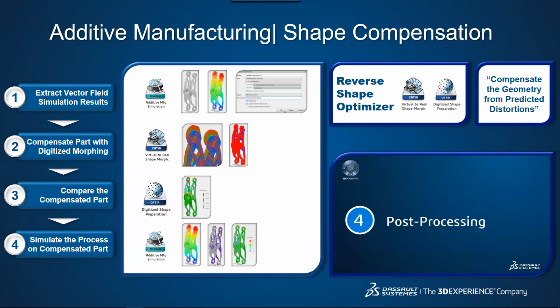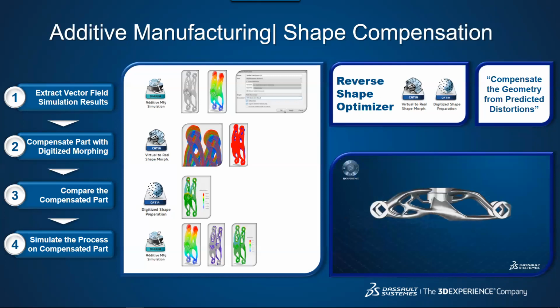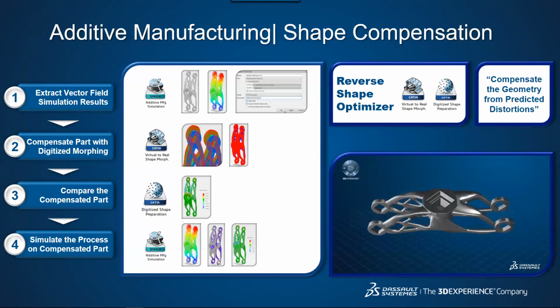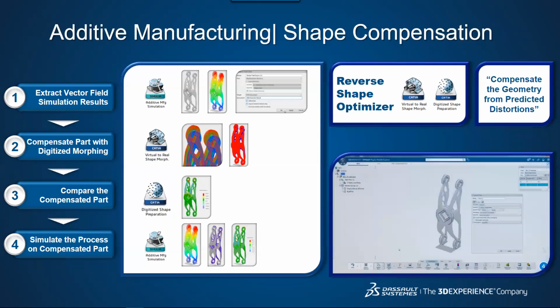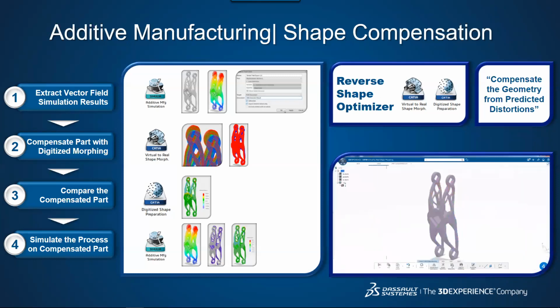We can compensate the CAD part based on a negative scaling of those distortions. So when you actually build that negatively compensated part, as it distorts during the build, it actually gets closer to your as-designed geometry instead of further away. Because this is a nonlinear process, you may have to do this iteration loop a couple of times, but we have this set of tools that allows you to do that.